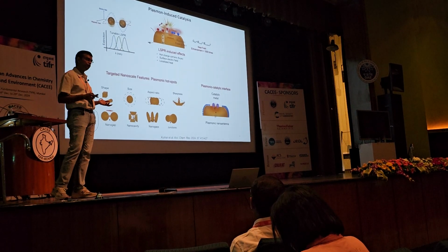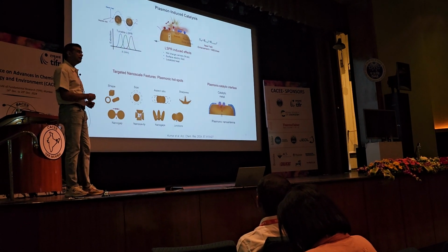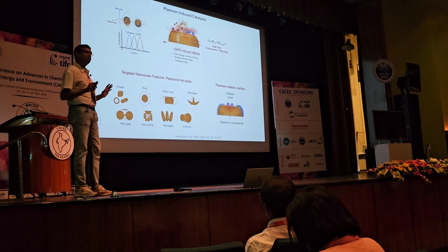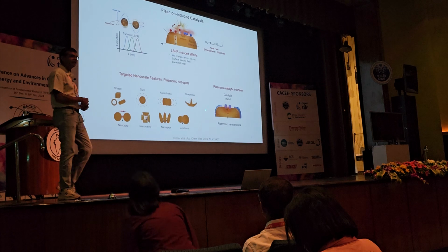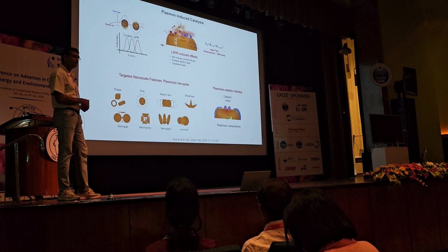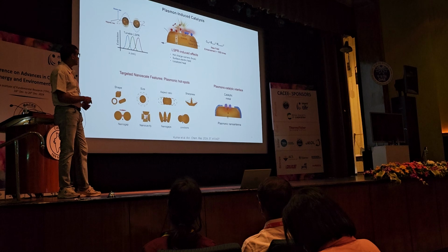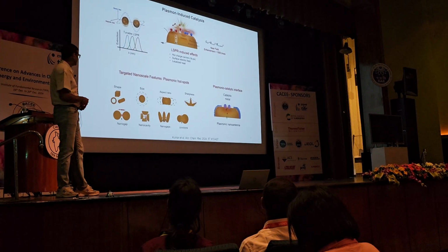within the same nanoreactor. But unfortunately, this kind of capability is available only in certain metals like gold or silver, which have limited catalytic power. So we want to interface some catalytically active metal with the plasmonic core, and based on this interfacing chemistry, you can control how the energy gets transferred to the active sites.